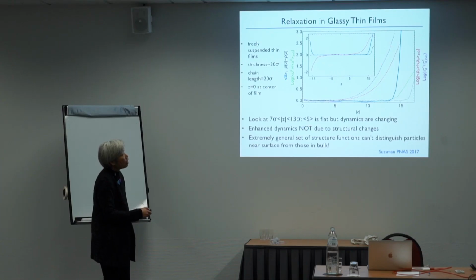This is the relaxation time. And so you see that as you go towards the edge of the film, 1 over the relaxation time goes up, the relaxation time gets shorter and shorter and shorter. The dynamics speed up as I go to the edge of the film.